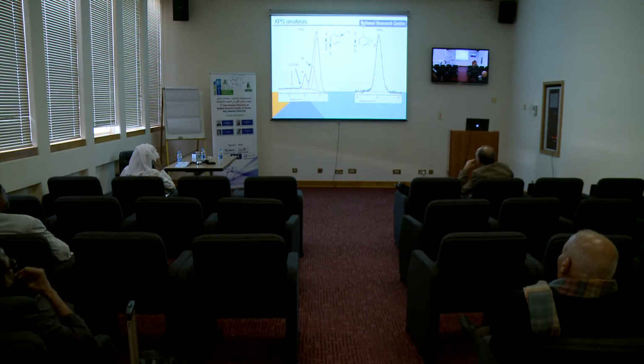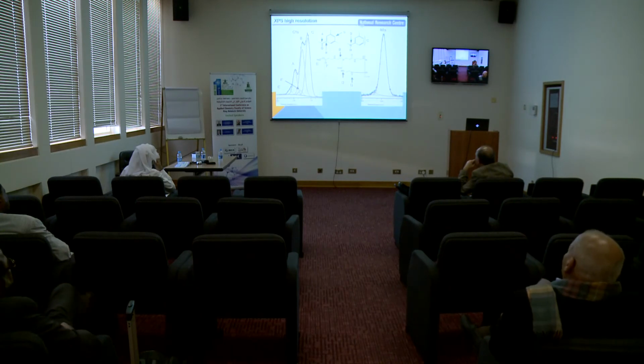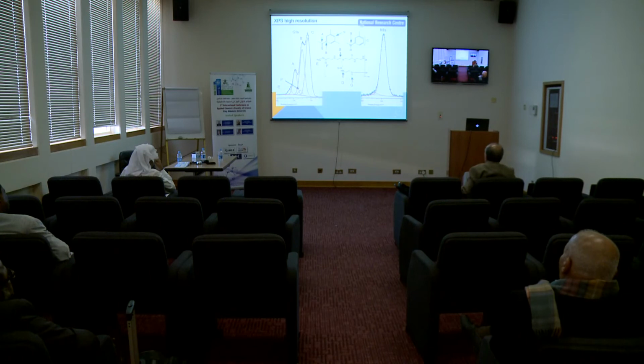Here is the assignment of the atom types in the aromatic polyamide groups of polyamidoamine using XPS. We did this for the polyamide layer without modification, and then we also did this for the modified membranes. And in these spectra, we can see the new signals for the carbons and the nitrogens. In the carbon, we can see the new environment, or new groups, for the carbon attached to the carbons of the polyamide groups, coming from the reaction of the amine of the polyamidoamine with the carboxylic groups. So this is a confirmation for our reaction, or for our grafting process.